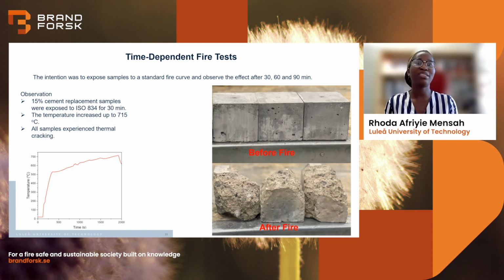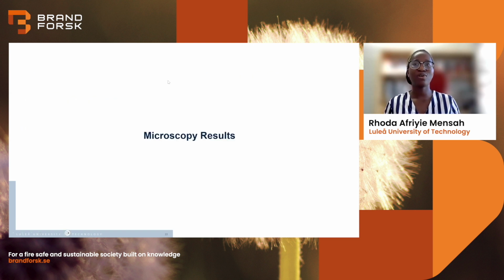And after doing the test, we realized that from the graph on the left, we see that the temperature increased up to 715 degrees Celsius. But after the test, we realized that all the samples experienced thermal cracking after 30 minutes. So it was obvious that after 60 or 90 minutes, we would have experienced the same results. So we didn't continue with the rest of the test. So Isaac will take this part.